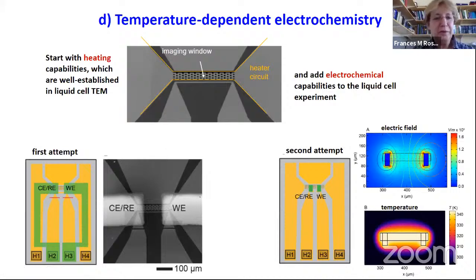So now I'm going to talk about temperature. We mentioned this briefly in the chat. I said that for us, a high temperature is like 100 degrees C. Liquid cells have been used for heating quite early on, but people have typically not done heating plus electrochemical experiments. And one of the reasons is that the heater circuit needs 2 electrical connections. The electrochemical experiment needs 3 or 4 electrical connections. You just don't have enough of them in typical liquid cells, but these things are changing.